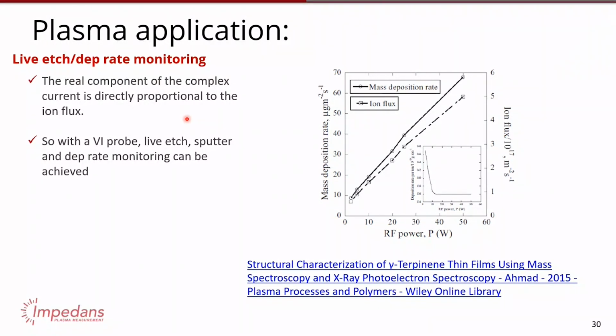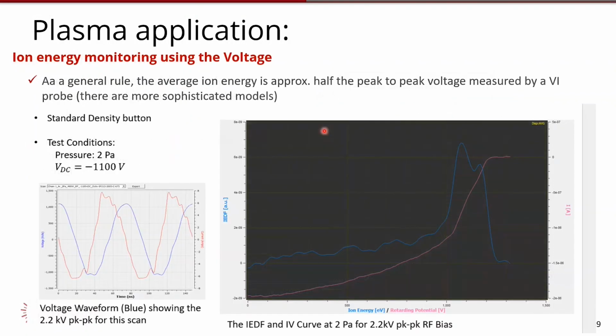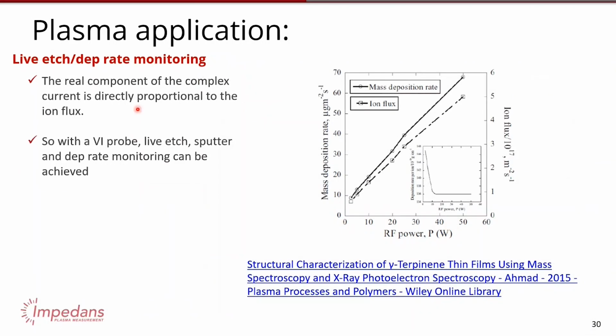And if you take the real value of the current of the probe, divided by the surface area of the electrode, that's ion flux. And that's linear with etch rate, provided the ion energy stays the same. So if the ion energy is constant and your ion flux increases by 10%, your etch rate increases by 10%. Okay. And there are various papers showing this, not just etch rate, but also deposition rate. Here's ion flux and deposition rate plotted on the same graph. They're completely linear with each other.